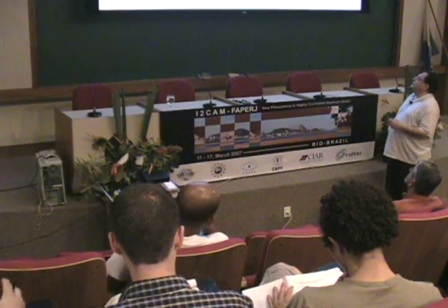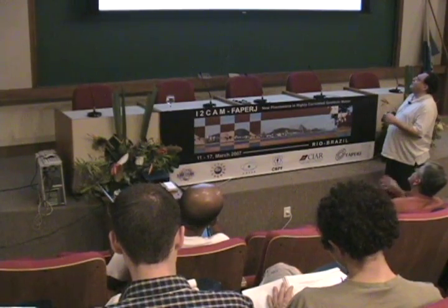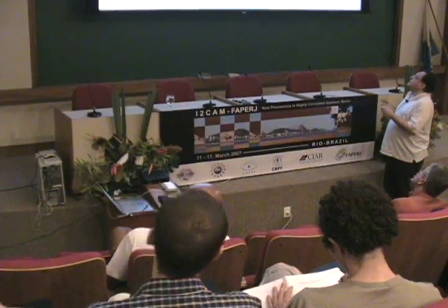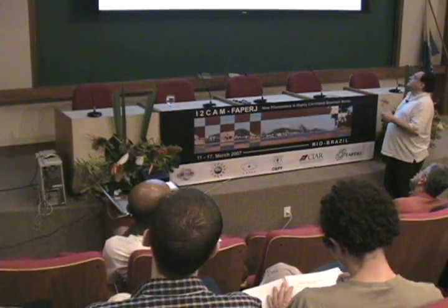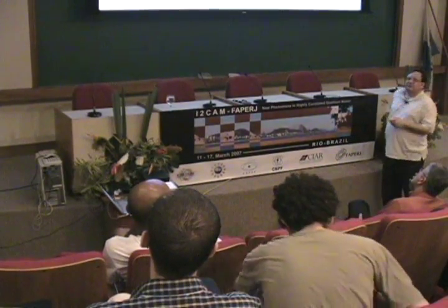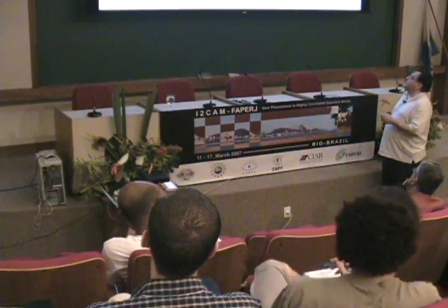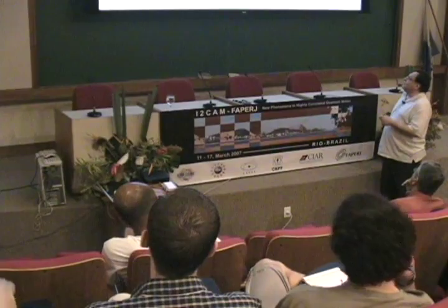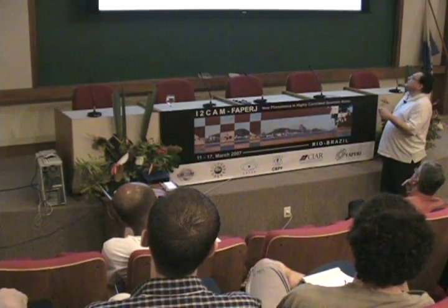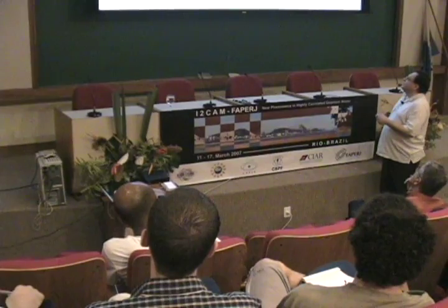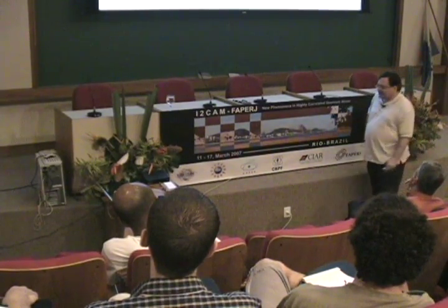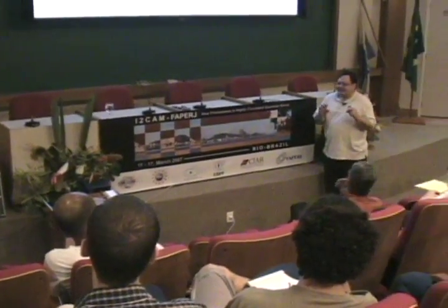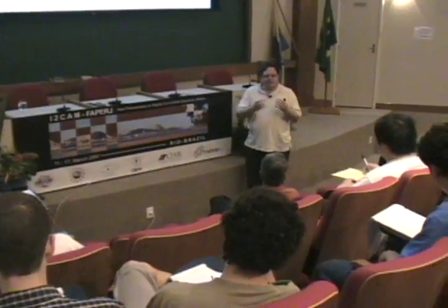the pseudogap we only know as a temperature scale, and compared to the superconducting gap, also in units of temperature, one just scales like the other. So everything scales with this energy scale, not with the actual TC, which is going down. This gap is increasing proportional to this one, but TC is dropping. So it looks to us at the beginning that perhaps the sample is getting ready to become a superconductor.